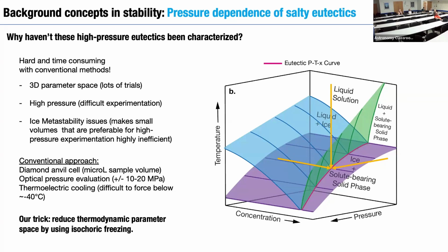So conventional approaches that people use for high pressure thermodynamics, like the diamond anvil cell or pressurized DSC, become very tricky and time inefficient when you're searching this large parameter space for this small amount of data, right? And so the original way that I got into this was that Baptiste approached me about a technique I was working on to reduce the number of tests that you have to do to search this parameter space.